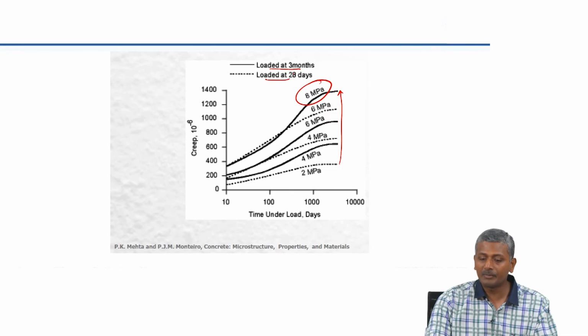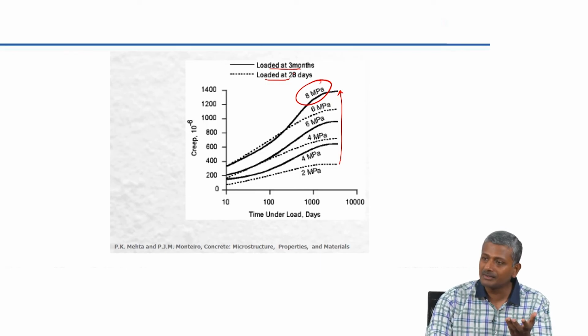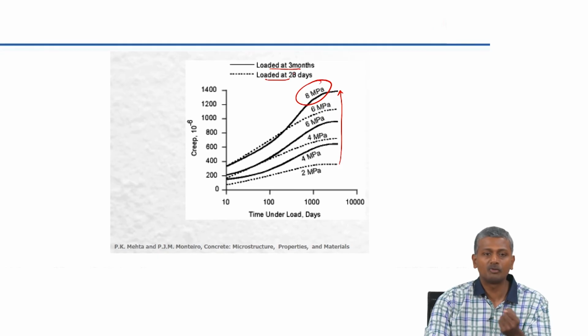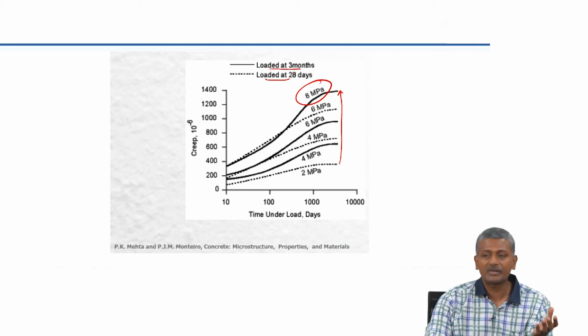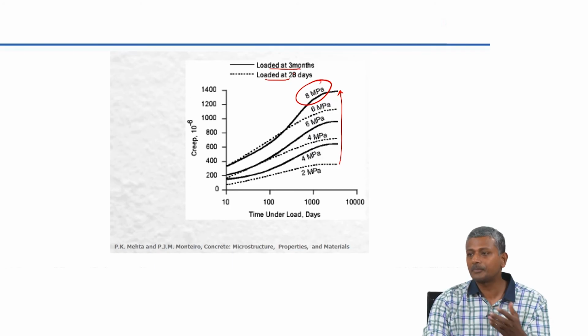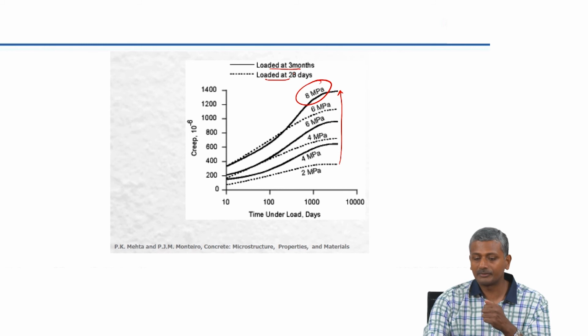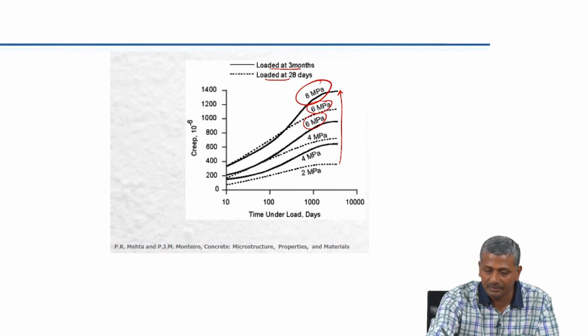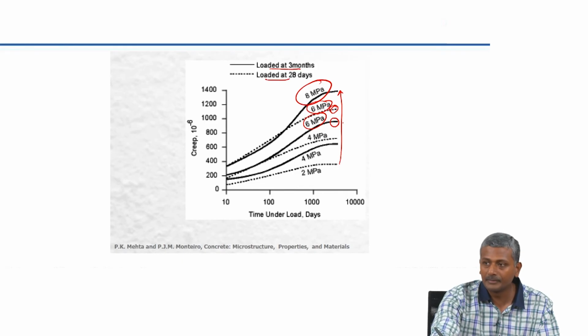When you load at 3 months versus when you load at 28 days. So, at 3 months what happens? At 3 months you have much greater strength, much lesser moisture available for movement. So, as opposed to 28 days, at 3 months you will have much lesser water in the system. So, the creep when you do loading at 28 days is higher than when you do loading at 3 months. So, if you compare 6 megapascal stress, at 3 months you have the lower curve, at 28 days loading you have the higher curve. Okay.